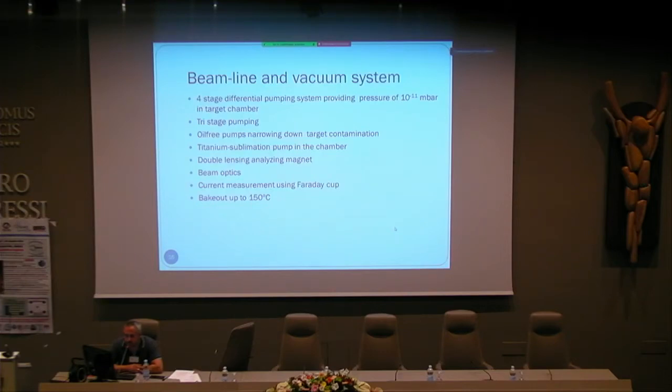Also, our chamber is mu-metal, which means that it's shielding our measurements from electromagnetic pulses or things like that. Of course, the pumps are oil-free, so we don't get any contamination with carbon layers building up on the target.